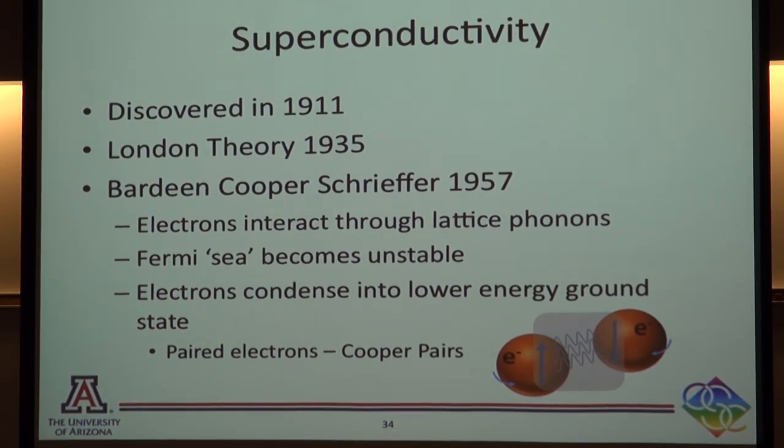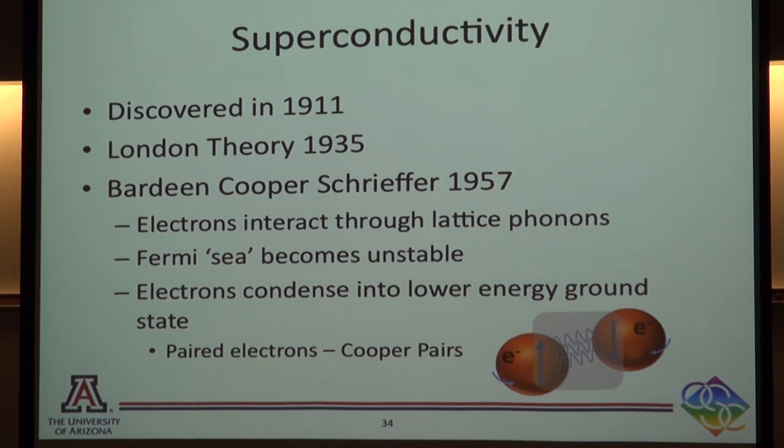In principle, I was used to thinking about light-matter interaction, and it's very different here. In some sense, it may help us avoid the thing which killed us with just putting a small metallic nanostructure on top of a semiconductor, because there you need to be within 5 nanometers to see any coupling, since it's through the field. Here, there is some hope that because of a Cooper pair, you can interact over much larger distances, at least 100 nanometers, or maybe even a micron. So far these were experiments by people doing real superconductivity with electronics, with either topological insulators or metals, but the distances are much bigger.